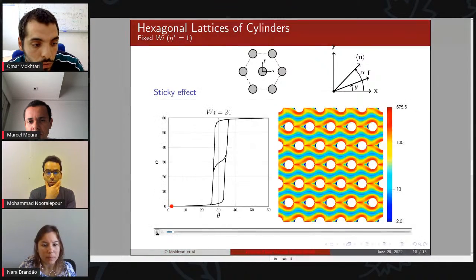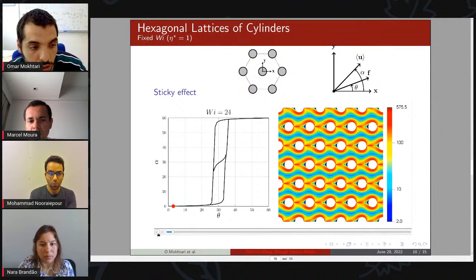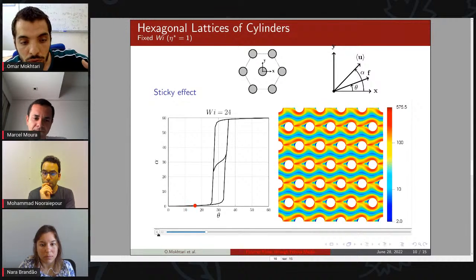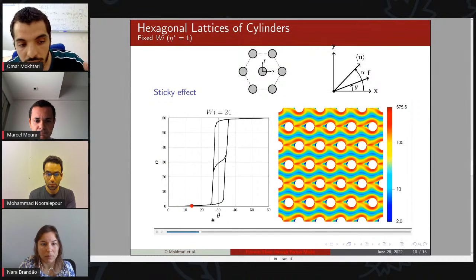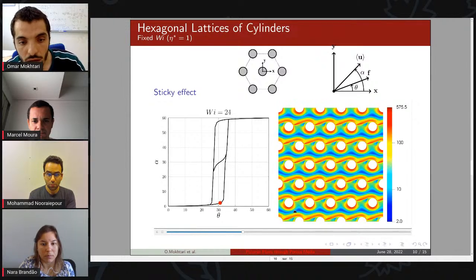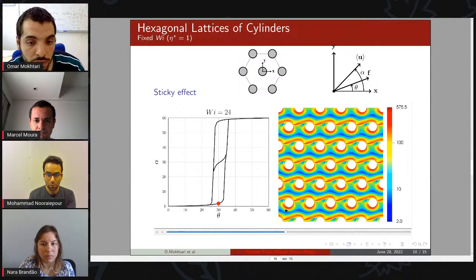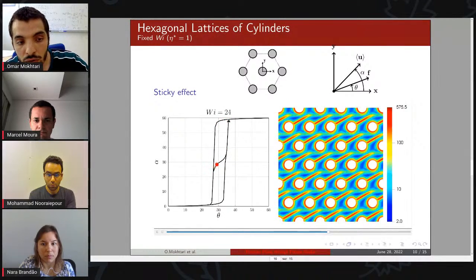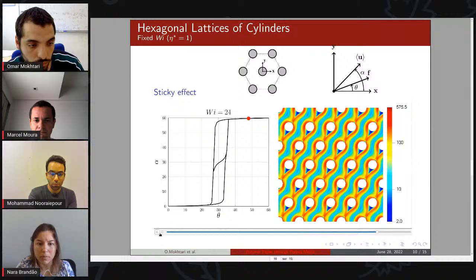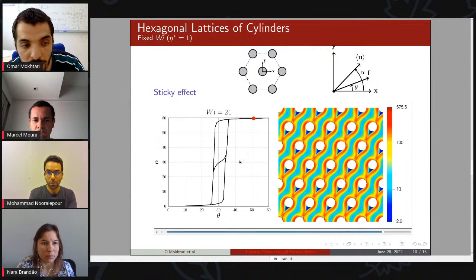Okay. Now, if we fix the angle, we fix the Weissenberg number, we fix the magnitude of F, and we increase theta degree by degree, we can see a sticky effect where the strands remain in the horizontal position until theta equals 30, and we have an abrupt drop-off of the strands, and at the end we have a second sticky effect at 60 degrees. We highlight the presence of a hysteresis on the angle theta.